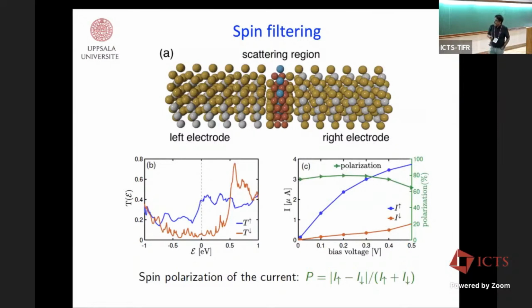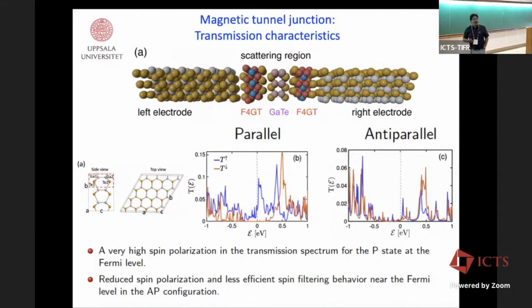And then comes the important question that everybody is talking about, the magnetic tunnel junction. What about the TMR, tunneling magnetoresistance? For tunneling magnetoresistance, you need a tunnel barrier in between the magnetic parts. Basically, a semiconductor, insulator, or vacuum. So we found out that there is a material, gallium telluride, which is also a layered semiconductor, which has a lattice parameter very close to this. And we have used this as a tunnel barrier in between. Then you have two magnetic layers here. In one case you align the magnetization in the same direction and calculate the transmission, and in the other case you do it in the opposite direction and also calculate the transmission.